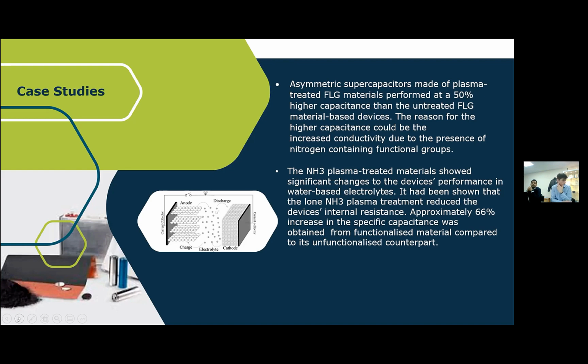And basically these types of functionalized material can lead to lower internal resistances, and in turn, that results in around a 66% increase in the specific capacitance obtained from the functionalized material compared to its unfunctionalized counterpart.